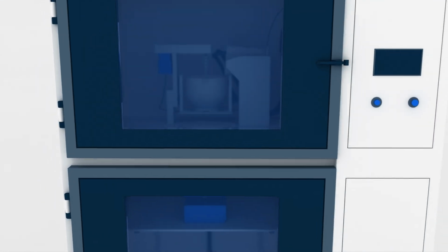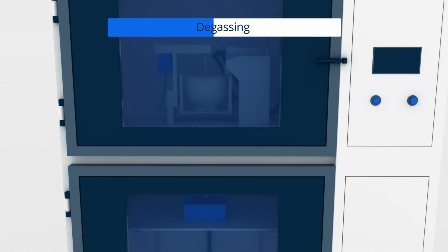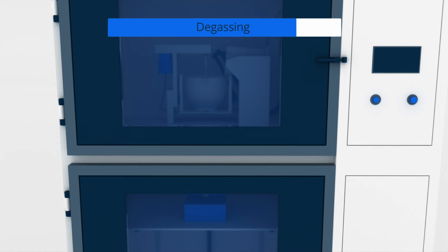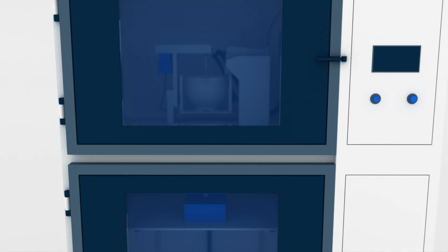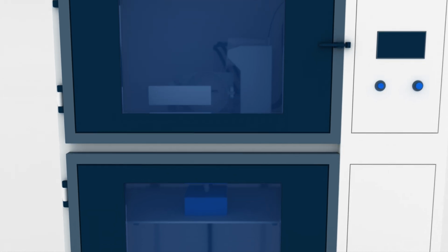After mixing, the resin is degassed in a vacuum chamber to eliminate any trapped air bubbles. At the same time, the silicone mold is kept in the chamber so it's immediately ready for casting once the degassing is complete. The mold with material is then exposed to high vacuum, primarily for clear materials, or high pressure to mitigate any bubbles that may remain in the liquid material.